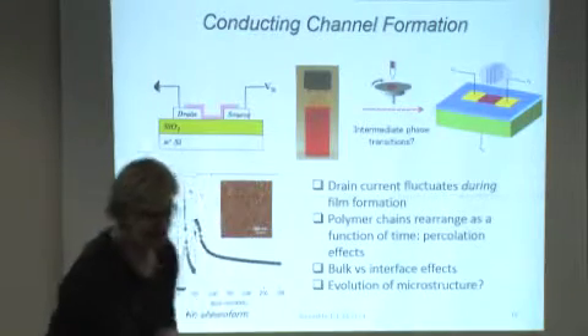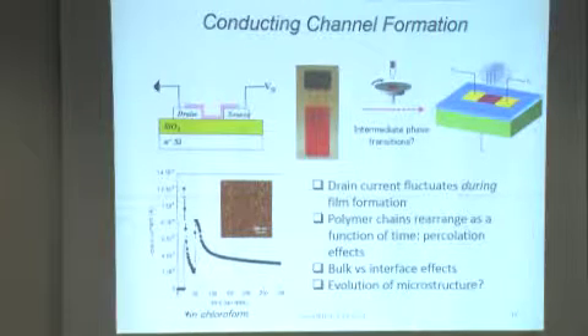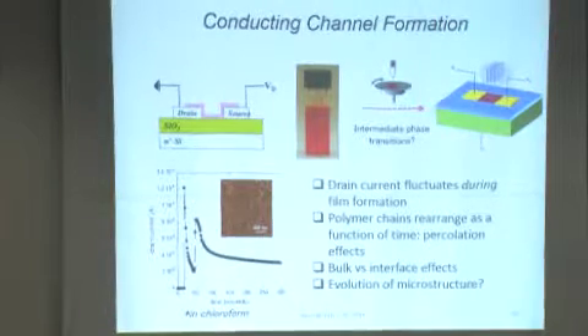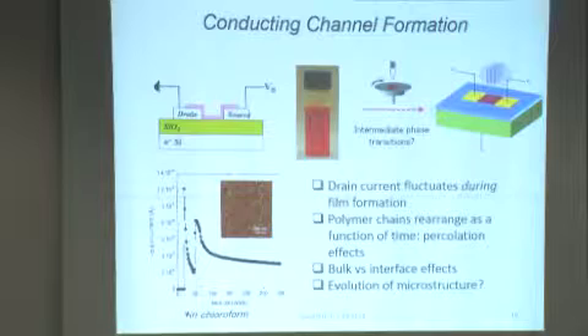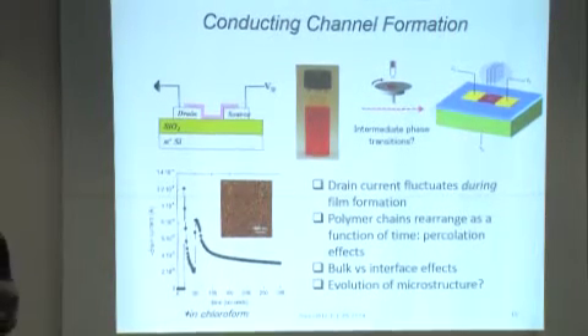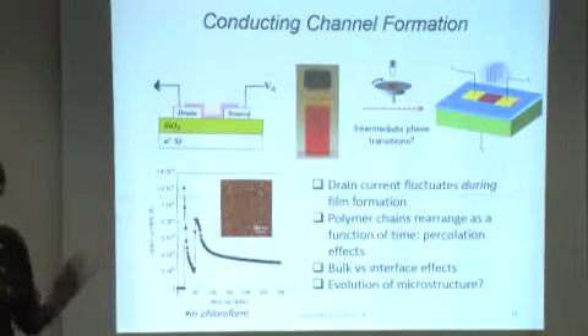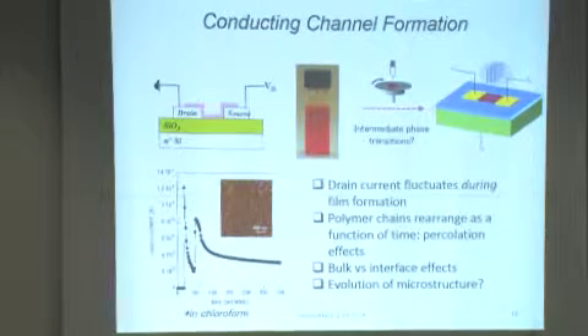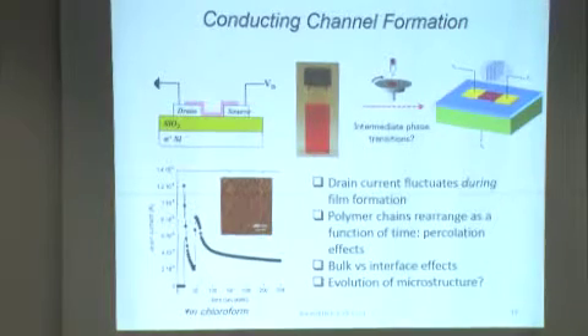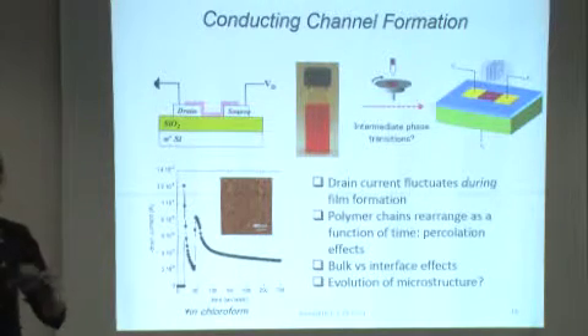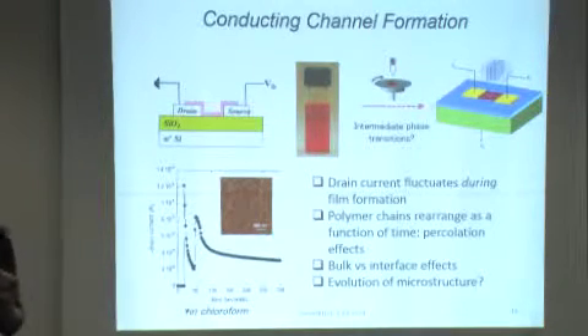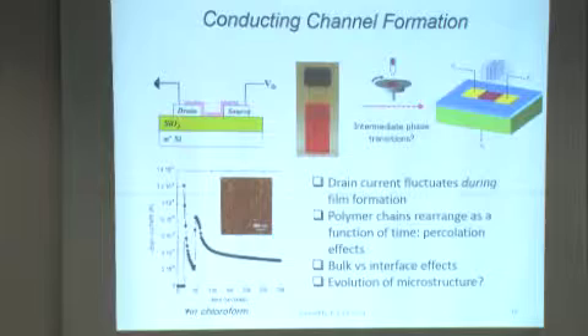All right, so we got our feet wet with looking at a little bit of processing, what you could do with processing to change charge transport characteristics. And then I started talking to Mohan, and we were intrigued about what may be happening in these films. So we decided to see what we might be able to do using charge transport measurements, but then also looking at in-situ Raman as solvent is evaporating, to see if we might be able to understand on a more fundamental level how these polymer chains are associating, and then does that association lead to changes in performance, and more importantly, can we control how those chains associate?